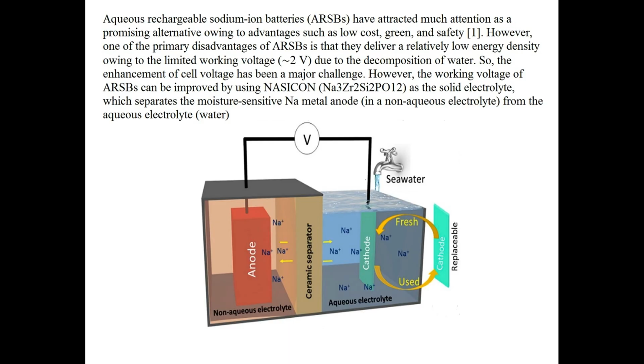Aqueous rechargeable sodium-ion batteries, ARSBs, have attracted much attention as a promising alternative owing to advantages such as low cost, being green, and safety. However, one of the primary disadvantages of aqueous rechargeable sodium-ion batteries is that they deliver a relatively low energy density owing to the limited working voltage, 2 V, due to the decomposition of water. So, the enhancement of cell voltage has been a major challenge. However, the working voltage of ARSBs can be improved by using NaSiCon, Na3Zr2Si2PO12, as the solid electrolyte, which separates the moisture-sensitive Na metal anode, in a non-aqueous electrolyte, from the aqueous electrolyte, water.